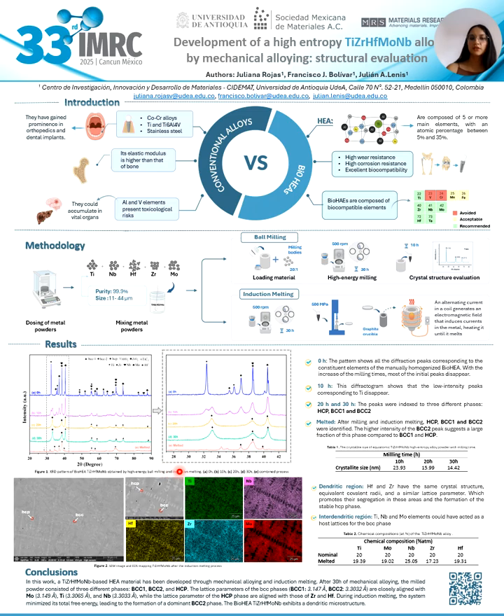After the combined process of milling and induction melting, peaks associated with BCC1, BCC2, and HCP phases were identified. In addition, low-intensity peaks associated with oxides and carbides of titanium and niobium are observed. The carbides were formed from the reaction between the metallic elements and the carbon from the graphite crucible used in the process. On the other hand, the higher intensity of the BCC2 peak suggests a large fraction of this phase compared to BCC1 and HCP phases.